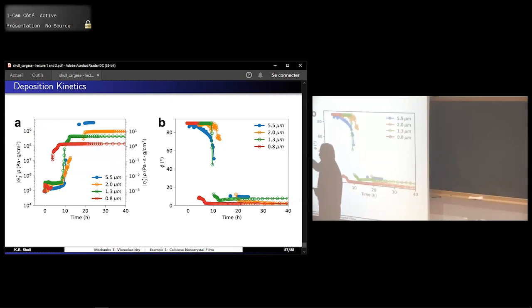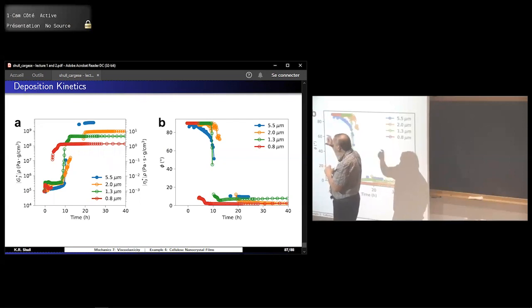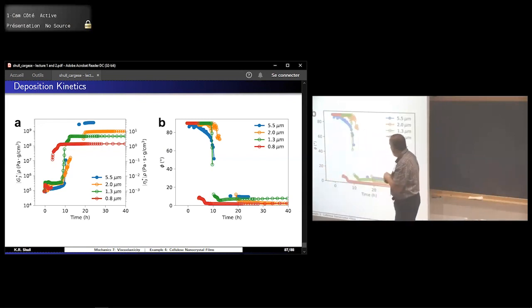Yeah, that's right. In this case, what we did is a two-layer model and say, okay, we always have a modulus close to this at the bottom. And then there's a layer at the top, basically one layer of the cellulose nanocrystal. But it looks like it's a factor of 10 down, so it looks like a 10 to 1 volume ratio. Yeah, that's right. So it's mostly a top dilute something and a very thin, stiff thing. And the phase angle? What is the other plot? The phase angle is also very different.